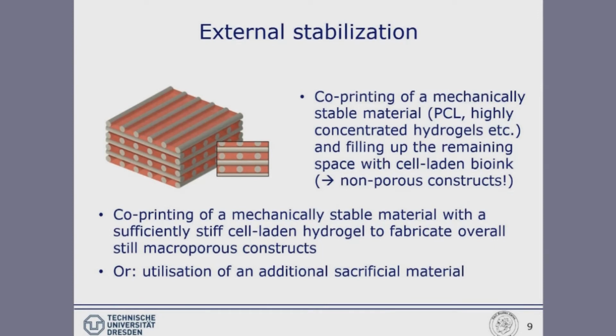And as we know that the cells, of course, would need oxygen and nutrients, we automatically will run into problems again if we would use this approach for real macroscopic scaffolds. Therefore, an alternative is not to use a very soft bioink, but a stiffer bioink, I'll show you an example later, so that we can still generate macroporous scaffolds. Or a third option is to use a third material, a sacrificial material, which is dissolved after printing and cross-linking, so that then again we would be able to generate open macropores, which would help to provide oxygen and nutrients to the embedded cells.